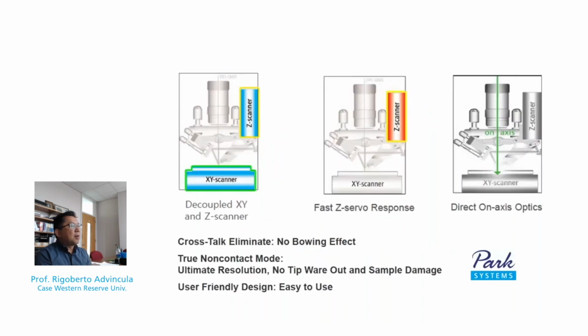But uniquely with Park systems, you have a unique design that has a separate Z scanner, XY scanner, which effectively decouples the XY sample substrate over the Z direction. The result is you have a very sensitive scanner, accurate, especially on the Z direction, so you can investigate trenches. There's no bowing effect. You have very high resolution. You tend to keep your tip for a long time, less sample damage, and of course, in many cases, very easy to use.